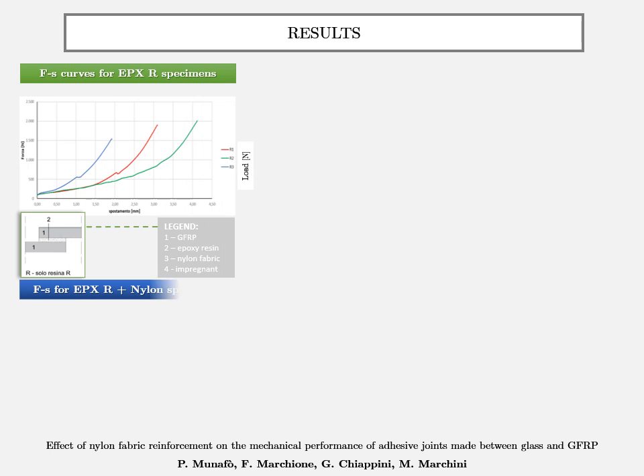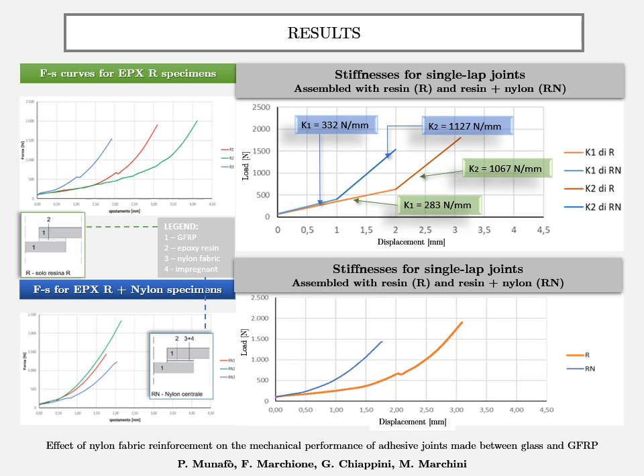The results from the shear tests on the single-lap joints are shown in the load displacement graphs for each configuration tested. To obtain the average stiffness value of the single-lap specimens, since non-linear behavior was found, the graphs of the characteristic curves were divided into two sections to calculate the trend lines. Then the mean value was calculated.